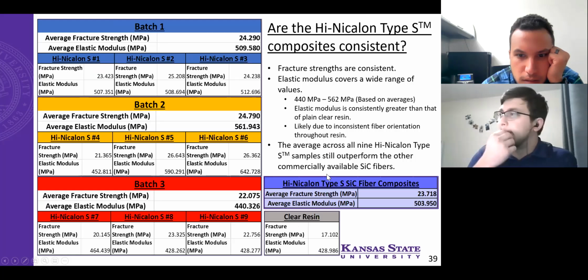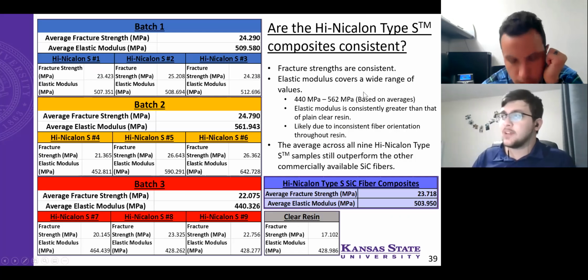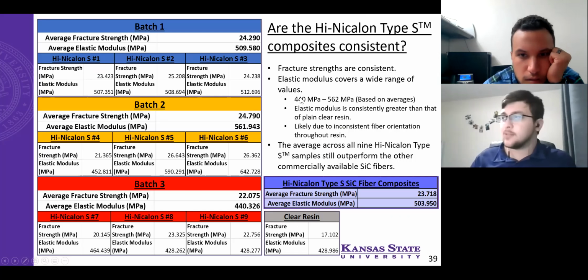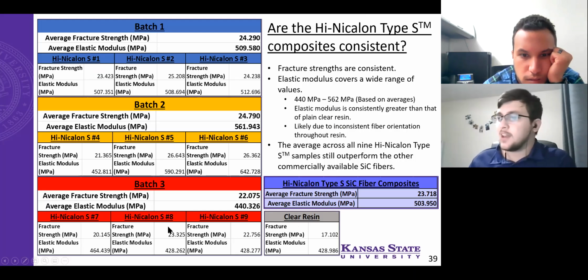I see. And here's just, are they consistent? The fracture strengths were consistent, but the elastic modulus covers a wide range, going from 440 megapascals to 562 when we're looking at the average, and 428 to 642 when we're looking at individual samples. And then I average that out here, or average all of them. They're still on average 503 megapascals, which is pretty consistent with batch 1.